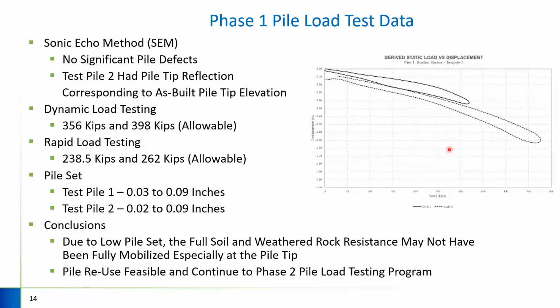So in particular, the results showed that the dynamic load test ended up getting about 350 to 400 kips allowable for the 2 piles. And that is obviously well in excess of the 300 kips we were looking for. And part of the reason for this is because we were using the dead reaction masses as our driving force. We ended up using 6, 12, 18, and 24-inch height intervals for the drop weight. And so the 18-inch increments were slightly below the required load of the 300 kips. And so we ended up increasing it to 24, which significantly increased the load imparted on the pile. And we backed that off in the phase 2 investigation.